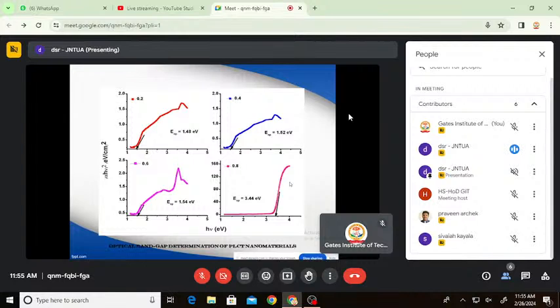there is a color change from sample to sample, and it might also be a reason for the partial change of optical band gap energies in the case of Z equals 0.2 to 0.6 contents, and the enhancement of the same for the Z equals 0.8 content.